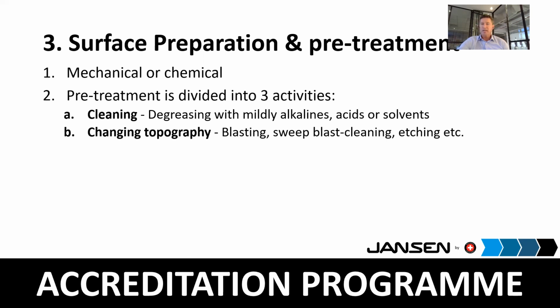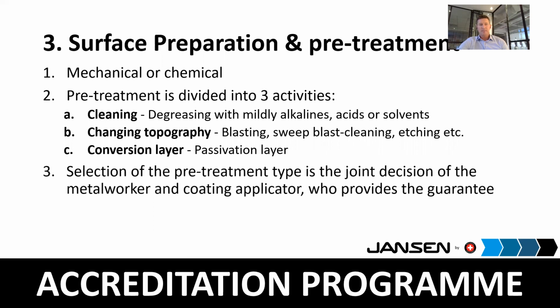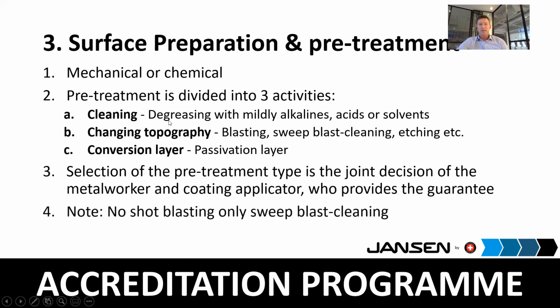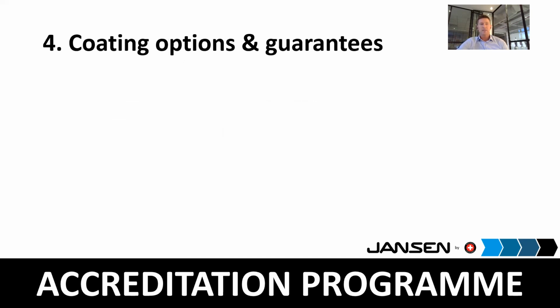You'll notice that you cannot sand blast this material as it changes the material surface too much. So sweep blast cleaning is more like a very fine grit, and I can't give you that grit offhand. Okay, the conversion layer is the third part of pre-treatment, and that's the passivation layer prior to treating. Now, the selection of your pre-treatment type is the joint decision, again, of yourself as the metal worker and your coating applicator, who will eventually provide the guarantee. And as a note, we said before, no shot blasting, only sweep blast cleaning with a very fine grit.